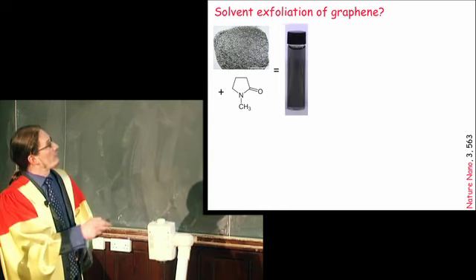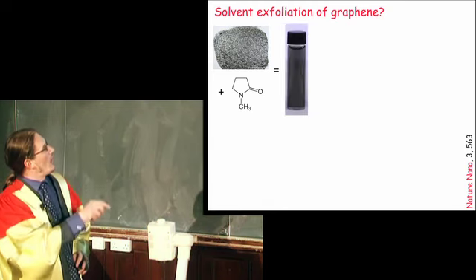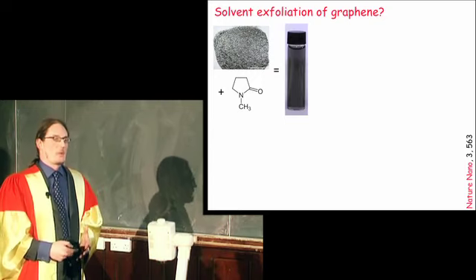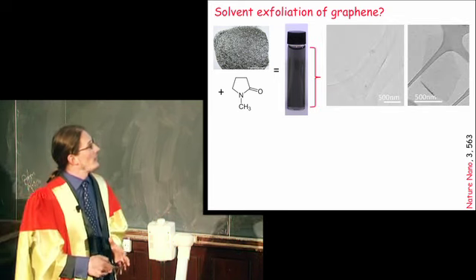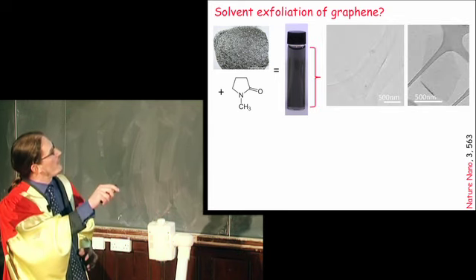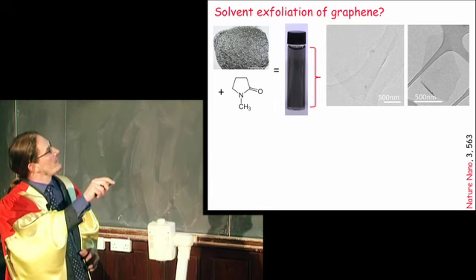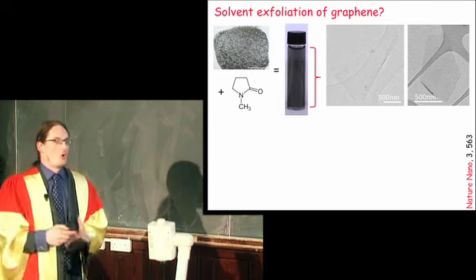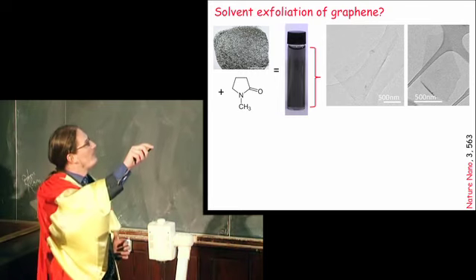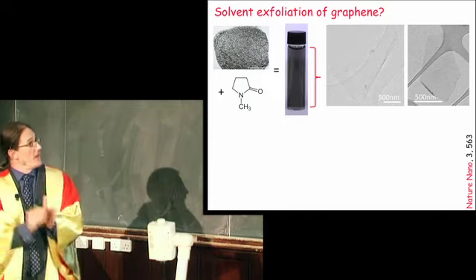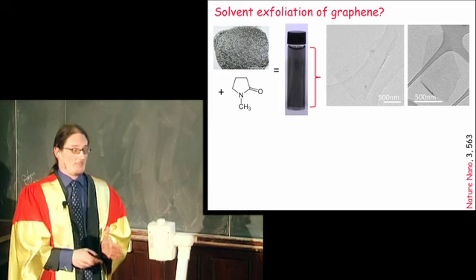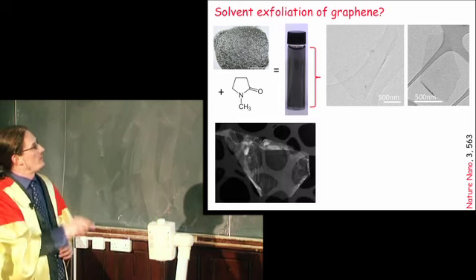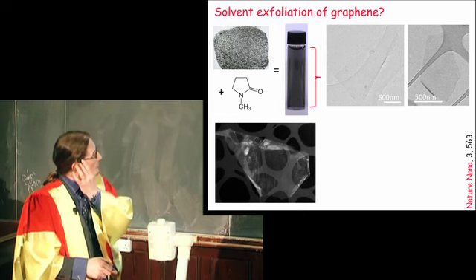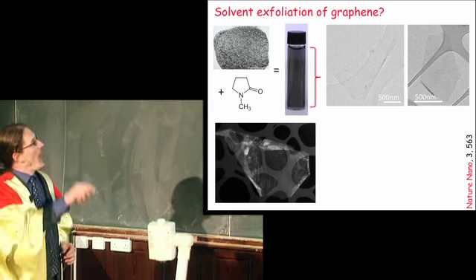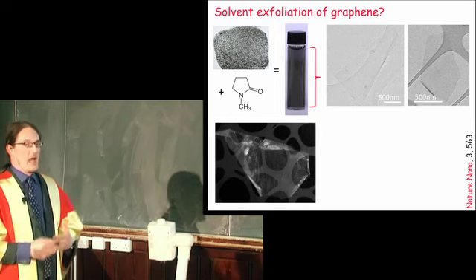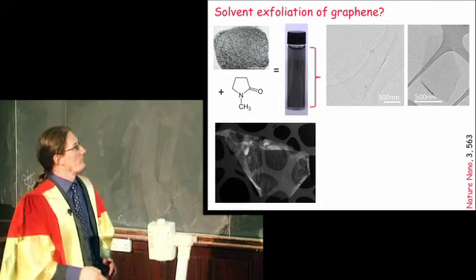So what we did was we used a sonication process to sonicate graphite powder in a solvent. You get a black liquid. The question is, does that black liquid contain graphene? So if you look in there and look at the electron microscope, you see you get very nice, well-defined objects that have straight edges. Now, straight edges don't normally occur in nature, certainly not for a good reason. And the reason you get straight edges here is because these are very, very simple systems which break along an atomic plane. Now, actually, you can do more sophisticated measurements, which were performed by Valeria Nicolosi, who's back in Trinity now after being in Oxford for a while. And she performed electron diffraction measurements that showed, without any doubt, that these are individual monolayers of graphene.